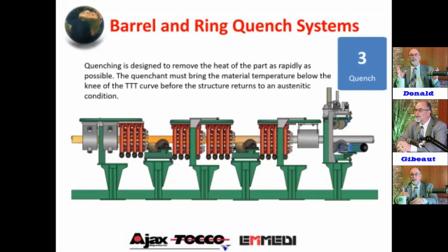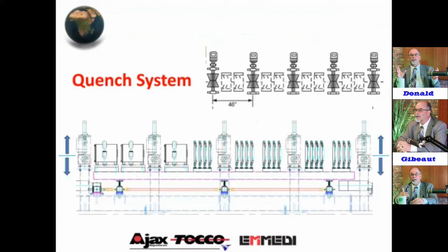Our basic design is a barrel and ring concept that we've been using for decades and decades, and we've been challenged over the years, but the bottom line is this system was contoured and designed to the TTT curve, the job that it has to do, which is very aggressive. Here's the quench now. When we talked about that 2 full revolutions of the induction coil to normalize out the heat, you don't have that effect here in the quench. The quench must be aligned on the center of the pipe to get uniform heating all the way around. To that end, in our quench barrels, we have 4 baffles in there, and break it off so you can individually control around the circumference of that barrel and equalize out any differences. That's what's critical to getting the end metallurgy uniformity and the as-quenched sampling.